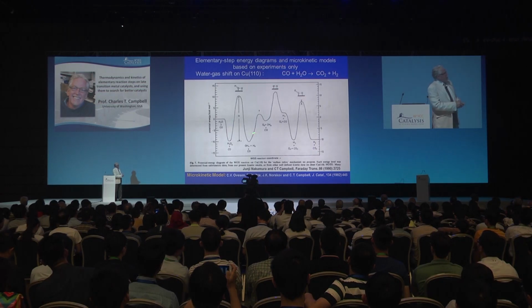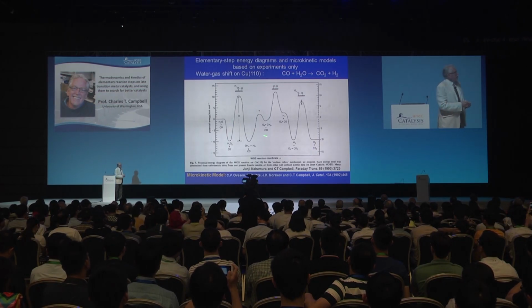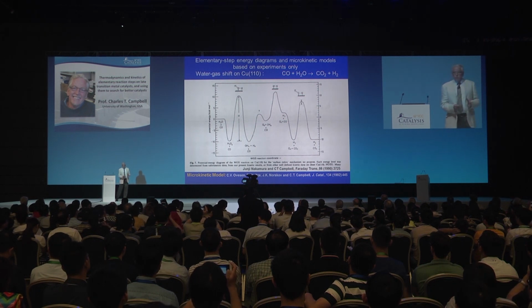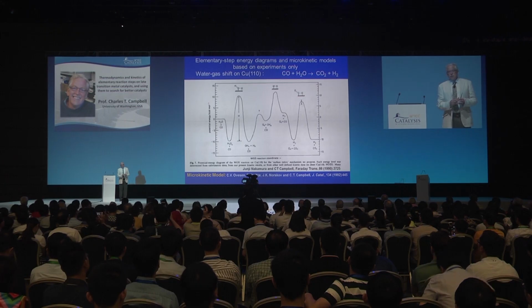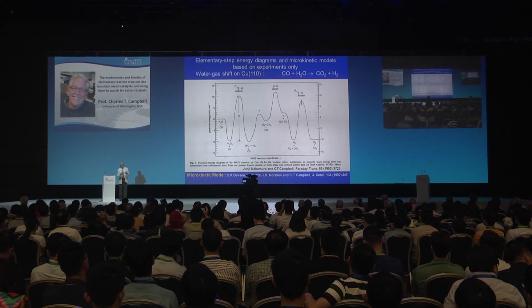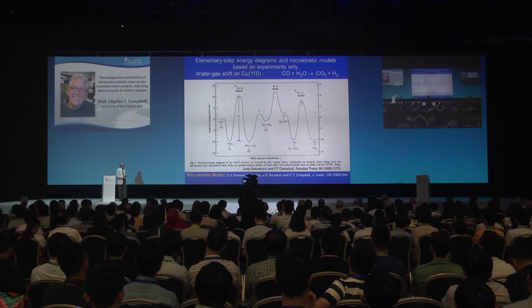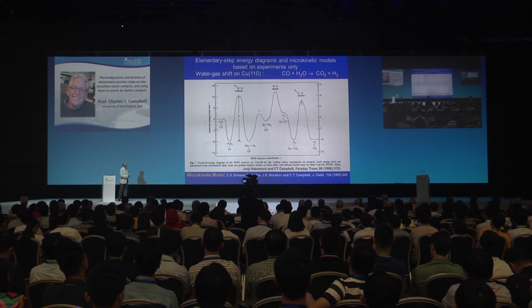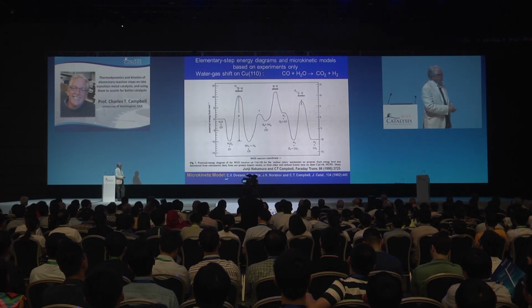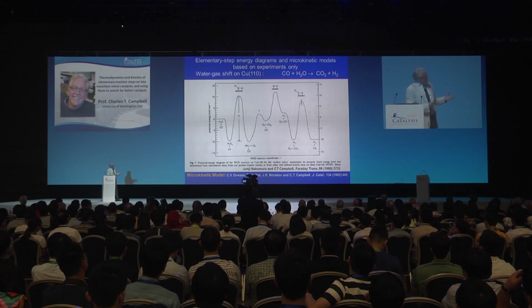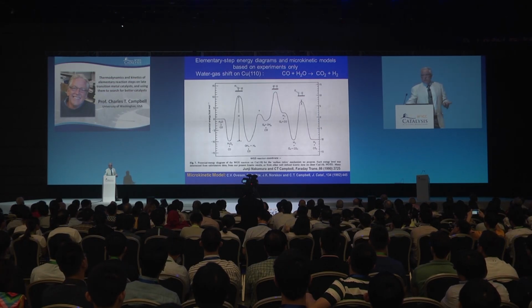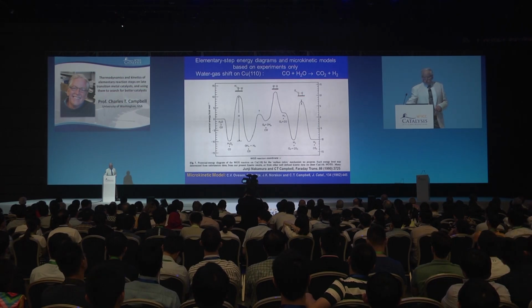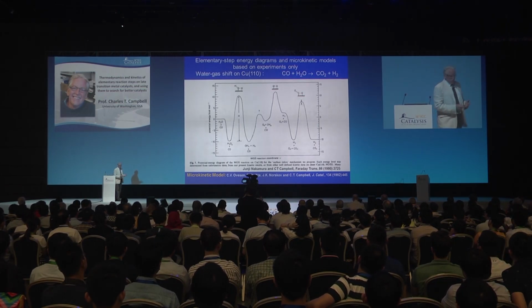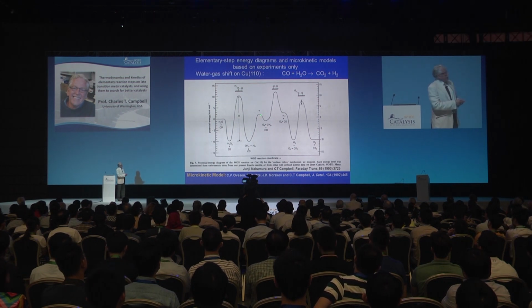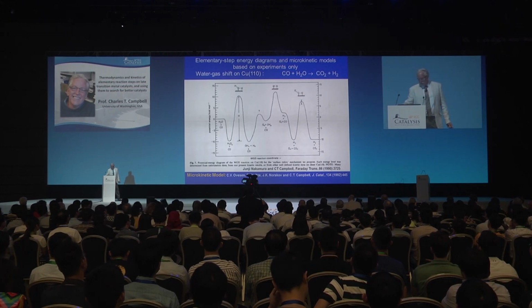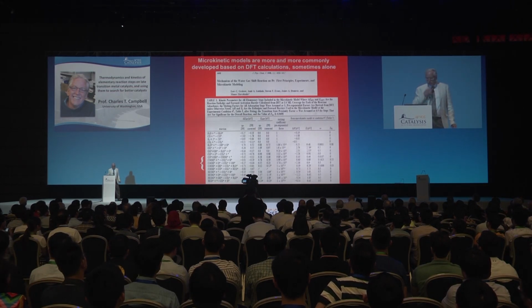And so these energy levels were all determined from experimental measurements, and we also measured pre-exponential factors for those, or obtained those from the literature. Could put those together into a computer to predict the reaction rates at different pressures and temperatures, and in fact found agreement with the experimental measurements of reaction rates highlighted in this paper here. And so this is what I call a microkinetic model, where you have all the elementary steps, all the rate constants in the forward and reverse directions for all those elementary steps. Or perhaps a better way to say that is if you know the standard state free energies of all the minima and the maxima in this kind of an energy diagram for the reaction.